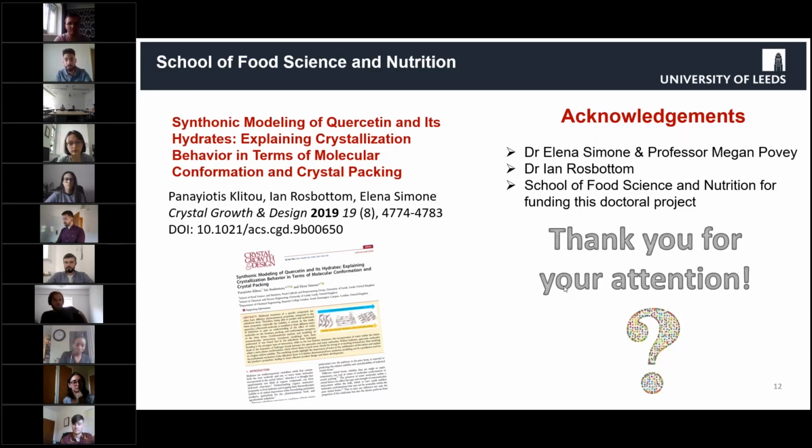So the form that we get after the desolvation of the dihydrate and the QDMSO is definitely a pure form. Pure meaning that it doesn't contain any solvent molecules. And since that pattern does not match with the anhydrous pattern of the deposited structure, it could possibly be a new pure polymorph of quercetin.